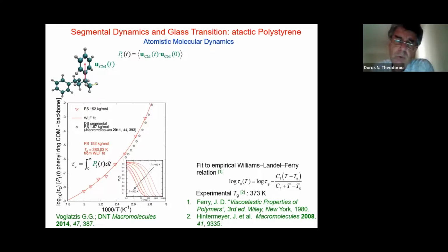And that is really the problem with glasses. And that is why we are trying to develop this landscape-based picture, because in theory, it would be able to track arbitrarily slow processes. When you do transition state theory, if you estimate the barrier correctly, it doesn't matter how high this barrier is, you see? And that's why we're really trying to develop this transition state theory approach, because it would give us access to very high barriers, which means it would enable us to look at the long time dynamics without doing molecular dynamics, because molecular dynamics necessarily will be trapped by the high barriers and give us something that is poorly relaxed.